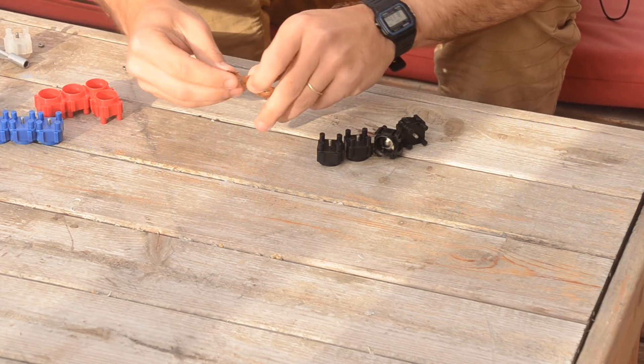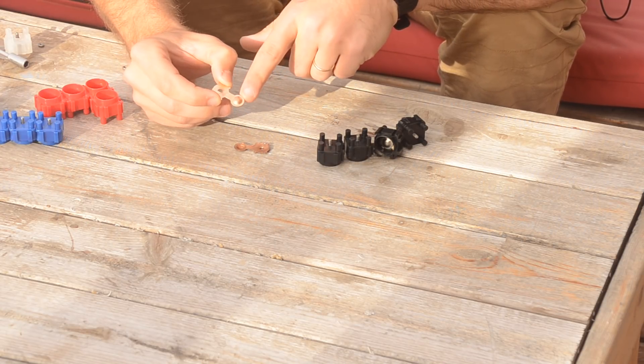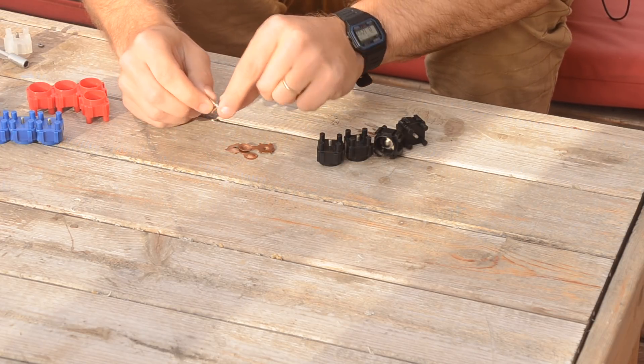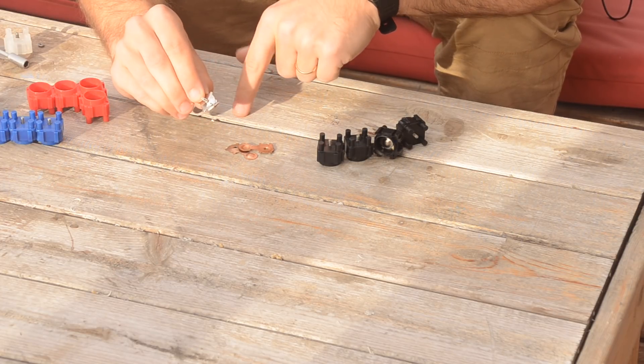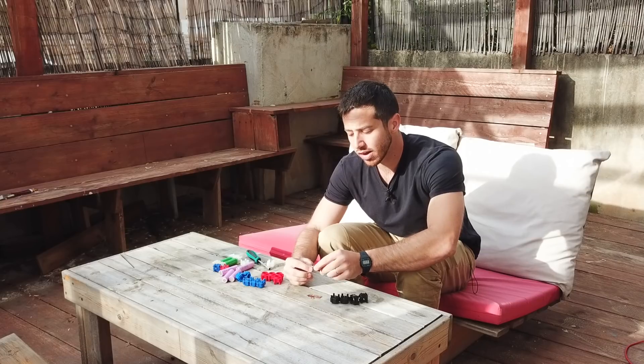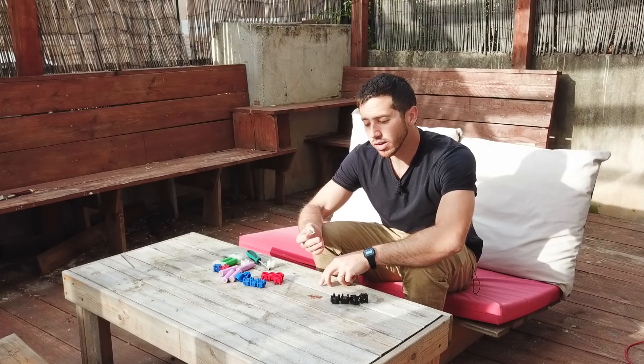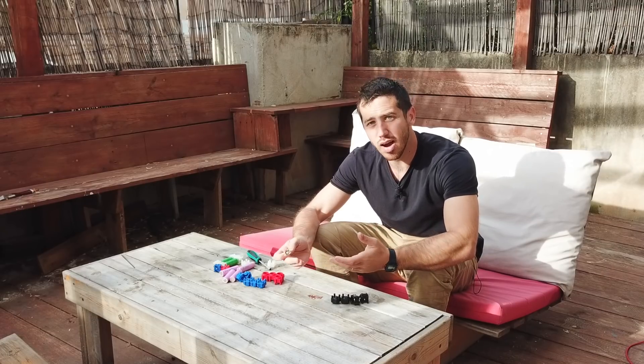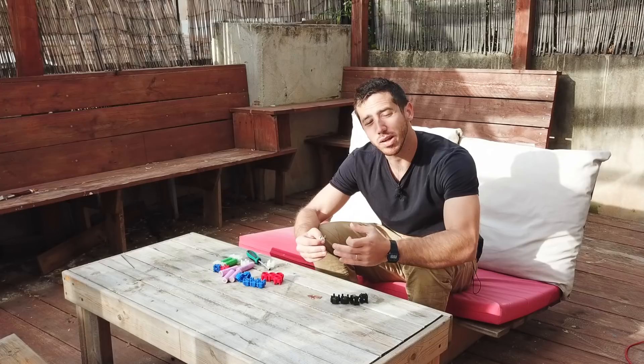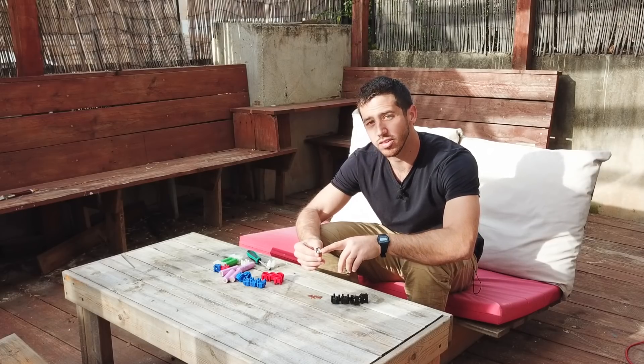These aren't like our old connectors — these are copper alloy-based, so these are going to be capable of much higher current. What we're going to do is actually nickel plate these. I've got a few here that already have the nickel plating on the copper alloy spring, and we're also using the same copper alloy for the threaded terminals. One of the production hiccups we're working on right now is the best way to connect the threaded terminal to the contact. On these ones so far we've been using silver brazing, which works really well, though it's a little more time-consuming. We're also looking at doing medium-frequency spot welding — you can't use a normal spot welder on copper or copper alloys. So we're looking at using a much higher quality, more robust medium-frequency spot welder. These will either be medium-frequency spot welded or brazed with silver brazing.